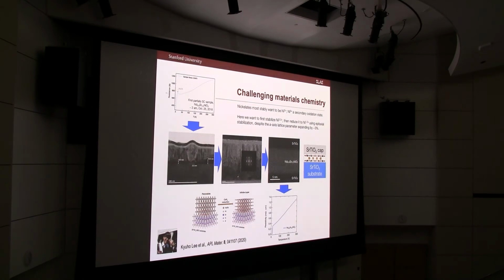Growing the strontium titanate, the second, there's epitaxy growing it? Yeah, but just to be clear, we're growing this on top in the perovskite form. So at that point, this is nickel O3. So this is our substrate. This is a thin film at that point of perovskite nickelate. And then on top of that, we grow strontium titanate. Then we reduce everything, but that reduction occurs just in the nickelate layer. I'm only showing you the consequence.